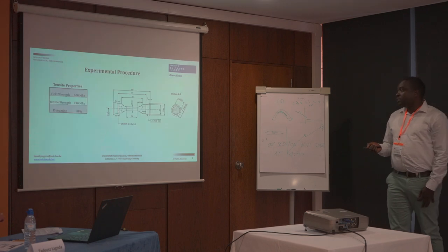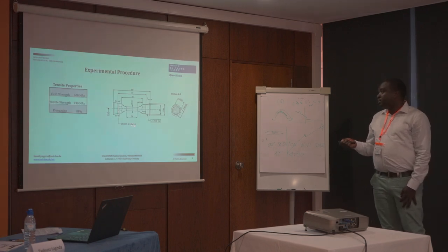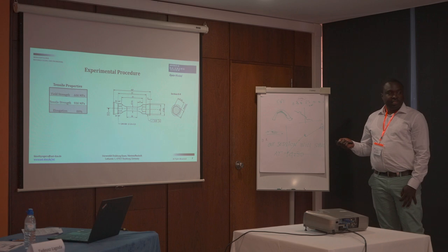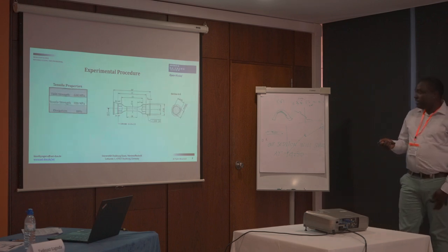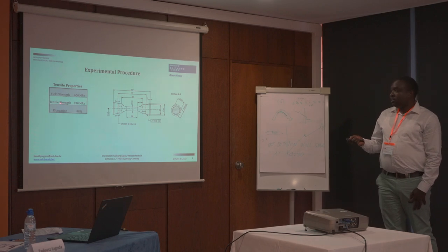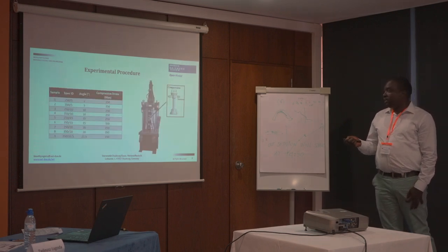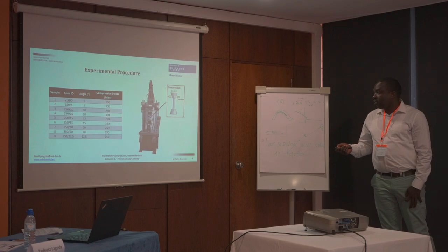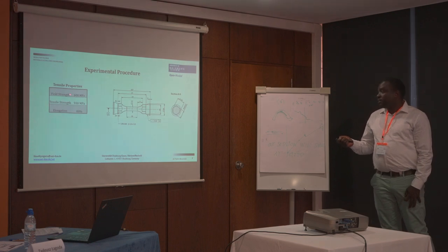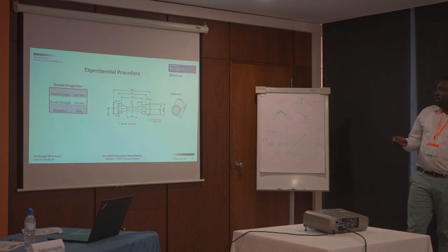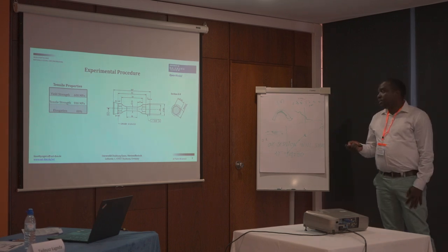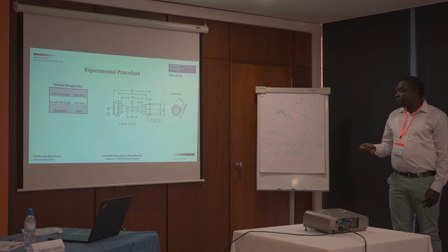So, the experimental procedure. This is the sample geometry that we use for the multiaxial fatigue. Before that, we had carried out some tensile tests and obtained these parameters. We saw that the yield strength of the material is about 600 megapascals, and the tensile strength is 930 megapascals.